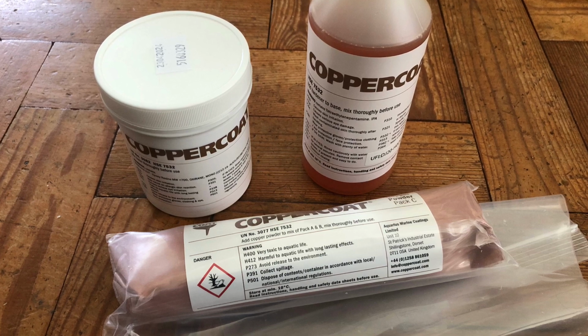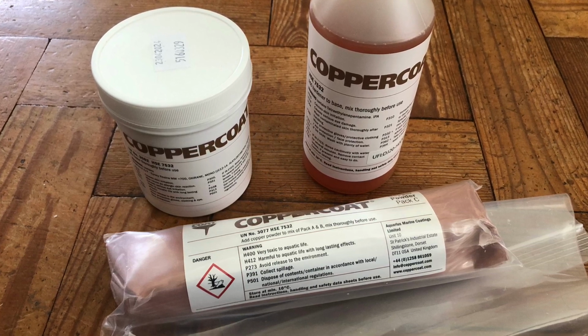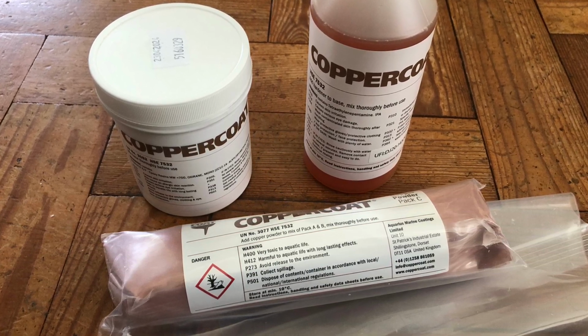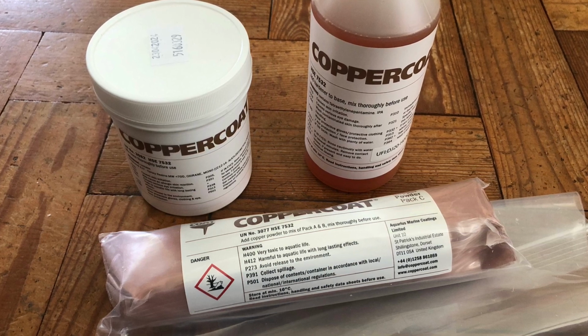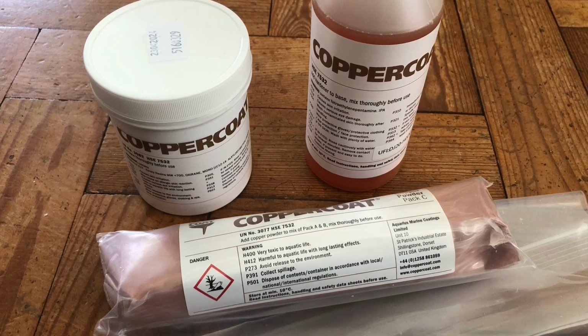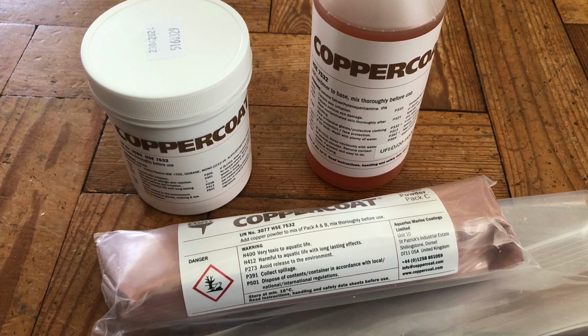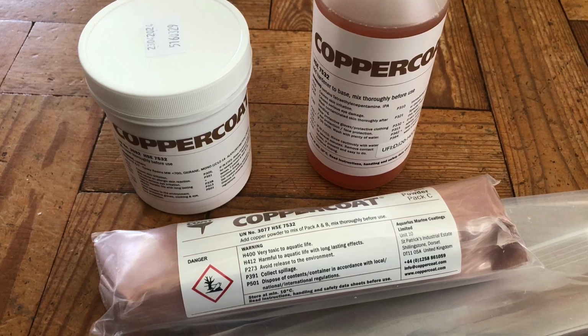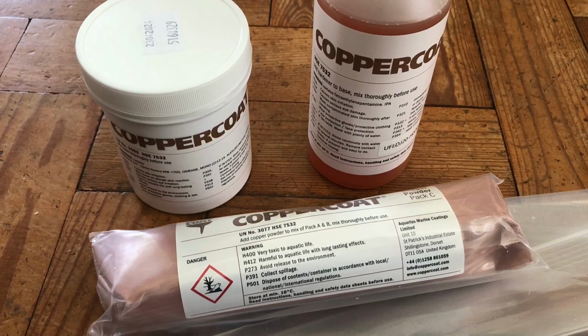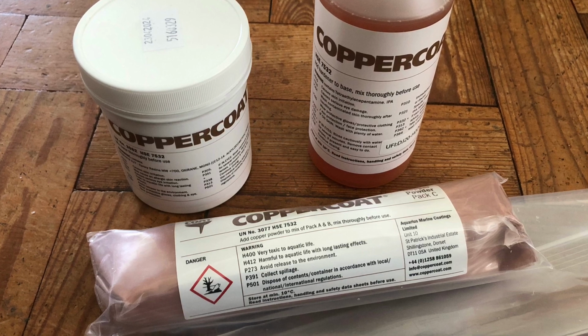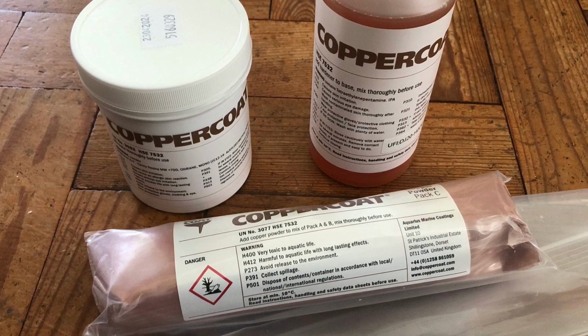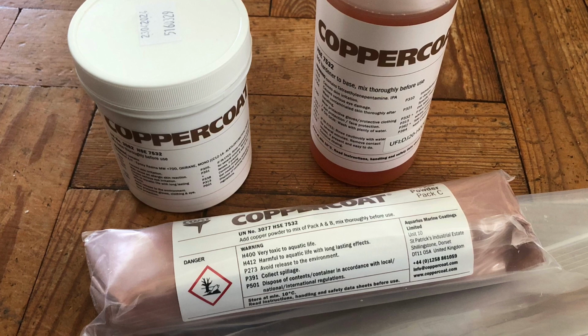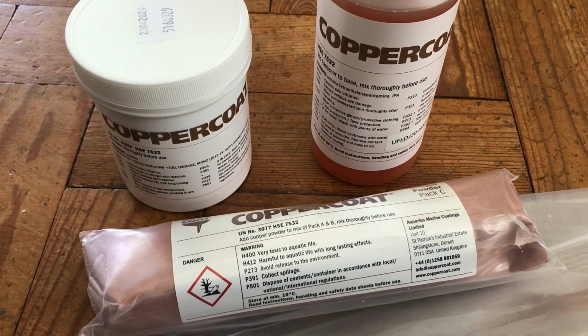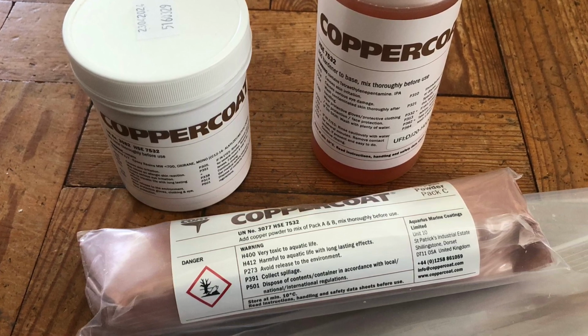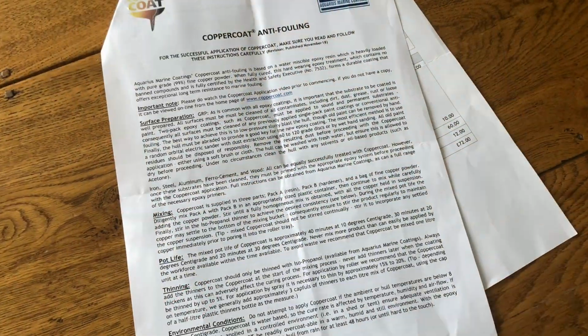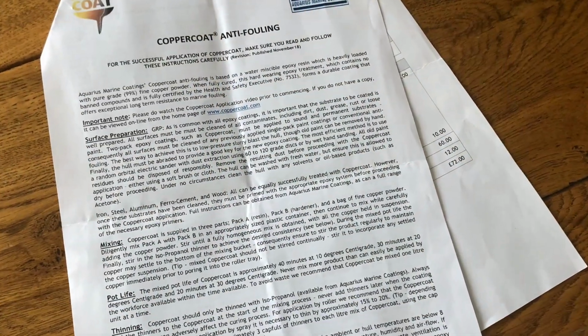Coppercoat is relatively expensive, so I ordered a small half-litre kit, which gives a coverage of approximately 1.75 square metres. The kit consisted of resin, hardener and fine copper powder. Coppercoat should be applied by spray or roller only, not by brush. I believe that using a brush leaves the copper at the bottom of the application layer rather than suspended throughout it. The kit also included comprehensive instructions.